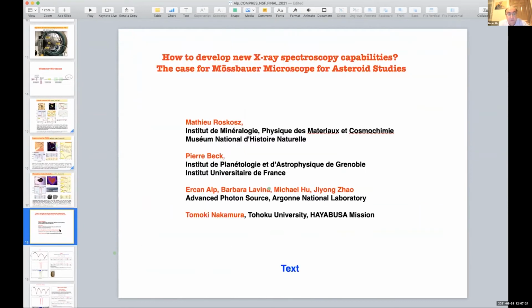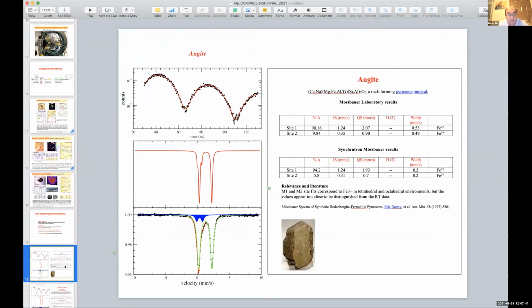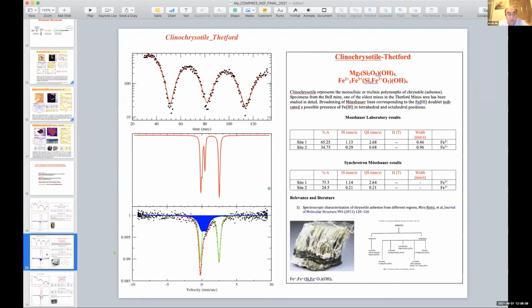So in the meantime, we set up a collaboration with the meteorite collector at the Muséum National d'Histoire Naturelle in Paris, Matthieu Roskosz, and Dr. Pierre Beck from Grenoble, where we combined our team and convinced Tomoki Nakamura from Tohoku University to include us in the Hayabusa mission. To qualify for that mission, we promised that we were going to look at a bunch of samples. For example, augite in the lab, in the beamline, 3+ and the blue one, 2+ iron. So we were able to get the ratios of 2+ and 3+ iron and the relative isomer shift and quadrupole splitting. So we repeated these measurements over the last year, 2 years, on various minerals with 2+, 3+ ratios.